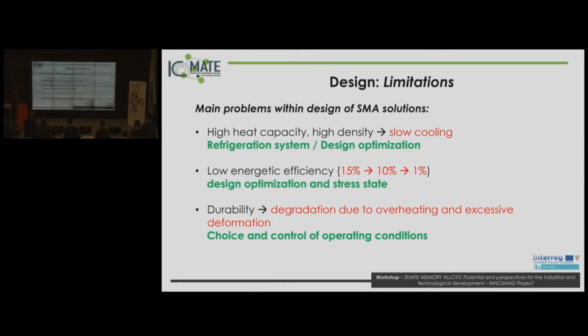The second limitation is the low energetic efficiency that we can face when the material is put inside a real device. And so again, we have to optimize the design, maybe by the optimization of the state of the stresses that the material has to face. The third problem when designing with SMA is the durability, since the material can be degraded due to overheating and excessive deformation that can occur during the use of the component. And so it's important to choose and control carefully the operating conditions.